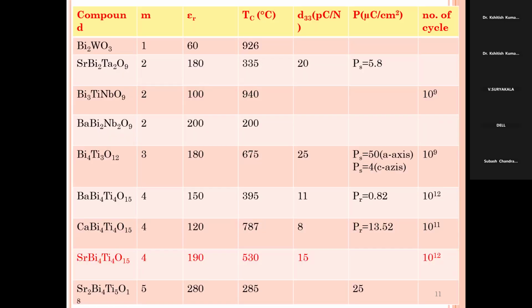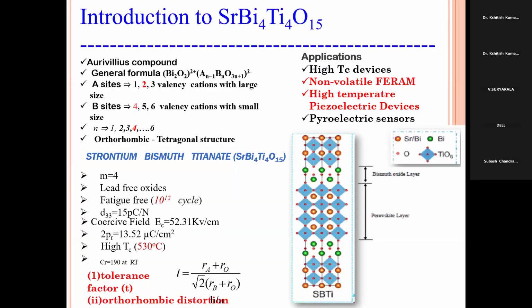So among the different types of materials, we have chosen the 4 layer structure, SBT, strontium bismuth titanate. The merits of the material: it is lead free, and lead is poisonous. The environmental people have banned lead, so we cannot use it in many materials. The next one is that it is fatigue free, up to 10^12 cycles. Then the D33 value is 15, the coercive field is 52.31 kilovolts per centimeter, and the polarization is 13.52 microcoulomb per centimeter square. High TC, as I have already told.